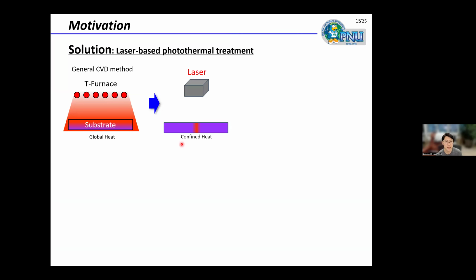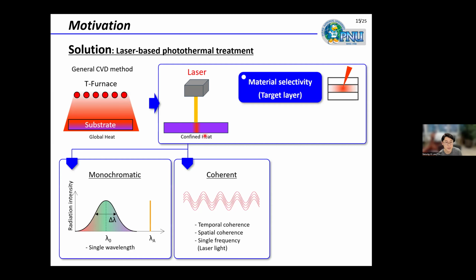We believe that many of these issues originate from the global heating system of the CVD process. Therefore, we replace the thermal furnace with a laser as the heat source to enable localized heating. Because lasers have monochromatic wavelengths and high temporal and spatial coherence, we can selectively hit the specific region of the target substrate. For example, even in the stacked three-layer structure, it is possible to selectively hit the mid-layer if it has a higher absorption at the laser wavelengths.